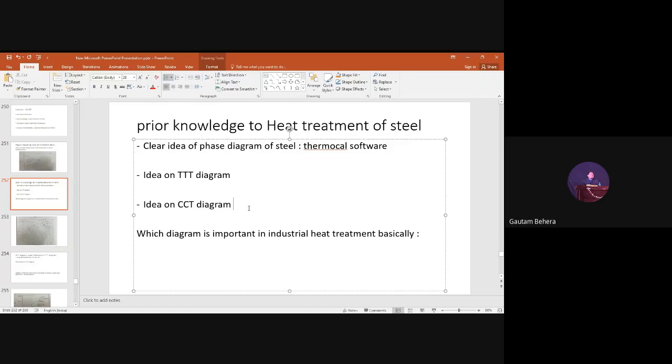That is one part, and another part is that on the industrial scale we also try to do things at a faster rate, right? That means the rate of production should be high. It is not like we will take a lot of time to do the heat treatments and all, right? So in the real industrial situation, we are cooling the steel continuously. We are not cooling the steel in isothermal conditions, unless we desire bainite in the steel for some specific compositions. We are not cooling from the austenitizing temperature in an isothermal condition. Basically, the steel is cooled continuously.